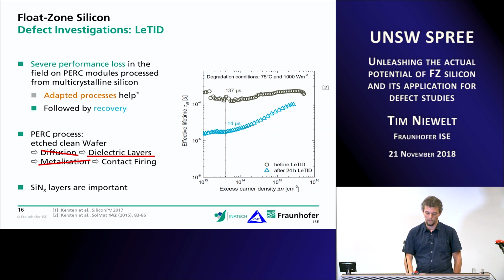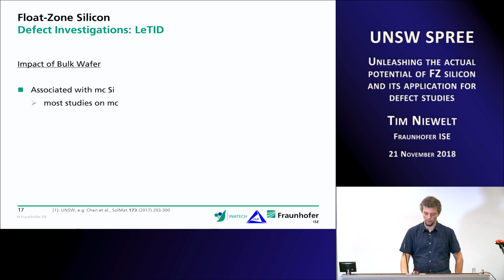need to be deposited. And yes, it has been shown in the past that the presence of silicon nitride layers that are widely used for PERC cells is important for the degradation. And the contact firing has been shown to be very crucial for the occurrence of the degradation. So it has been shown that the peak temperature of the firing process is affecting the degradation a lot. And then, yeah, of course, the wafer could be the problem. So let's look at the wafer first.